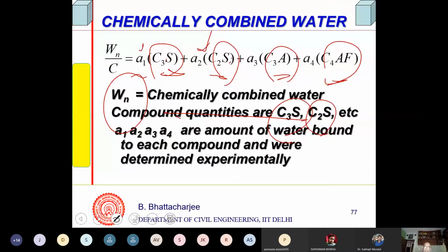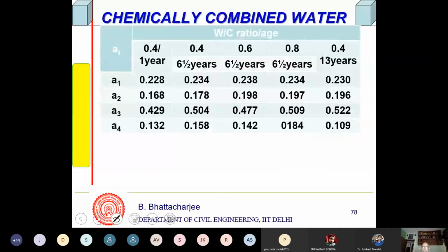So you can actually calculate out the bound water. You can calculate it knowing the proportion of C3S, C2S, C3A, C4AF, or knowing A1, A2, A3, A4, which have been determined by people doing very long-term experiments. This was done, I think, in France, if I remember correctly. I forget the name of the scientist, but this is available in Soroka's book. So you can see that they have done experiments up to 13 years. And they found out this A1, A2, A3, A4. And the quantum of water that reacts is somewhere like this.